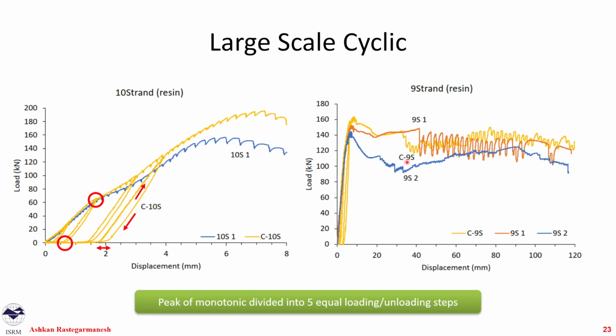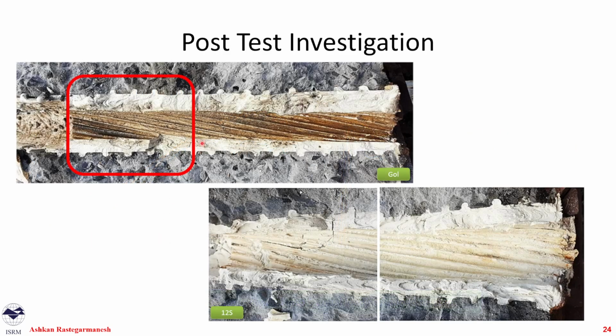So again, that's the example of our behavior that we can see and how our load pickups happen. For example, here in the 9-strand test, we see that most of them happen in the first 10 millimeters of the test. And again, the details of them are inside our published work. Post-test investigation for our cyclic test, again, we saw the same thing.